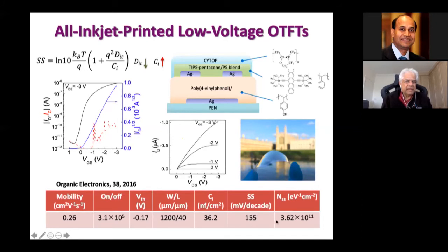So you're looking at 3.62 times 10 to the 11 for the interface state density associated with that transistor. And that was very important because when you bring down the density of interface states at the semiconductor insulator junction, you also bring down the voltage. So you can get very low voltage operation because the voltage drop across that interface has been minimized. So that's a very key point.